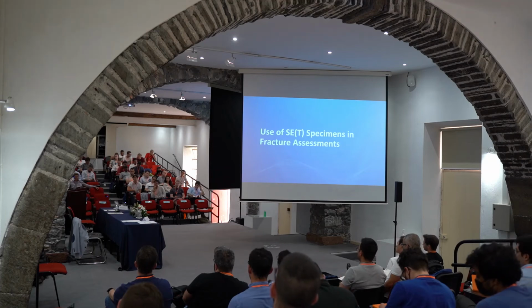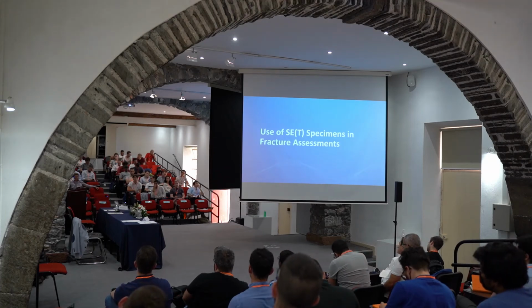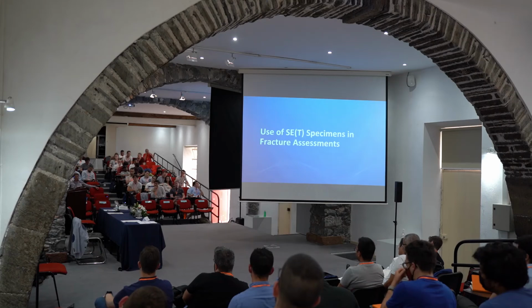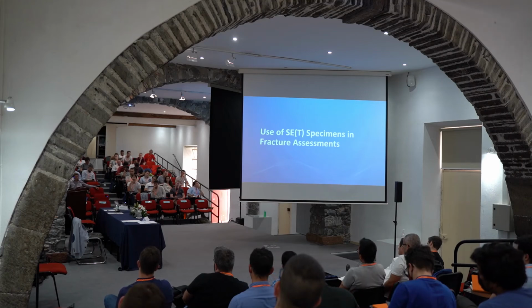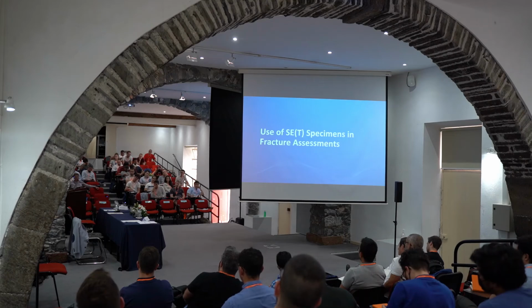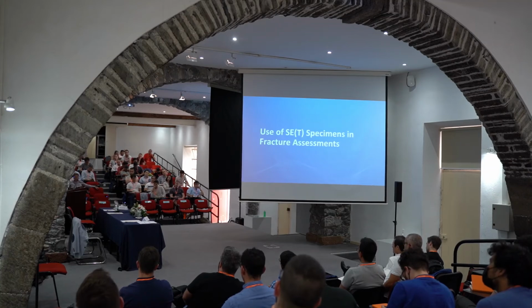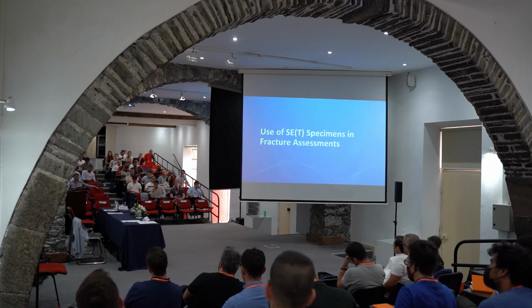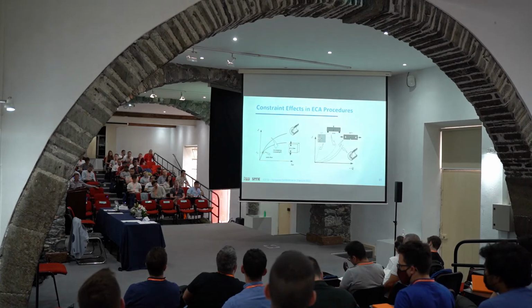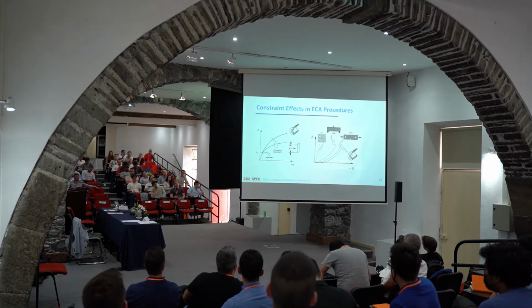And why is this important? Because if you have the same geometry, 3-point single edge, the fracture behavior changes dramatically if you change the loading mode from bending to tension. I'm not changing anything else. The material is the same, the geometry is the same. The drawing that you send to your machine shop is the same. The only difference is that instead of applying a bending load, like the 3-point bending, you're applying a tension load. It changes dramatically, as I'm going to show. And this is generally called constraint effects.